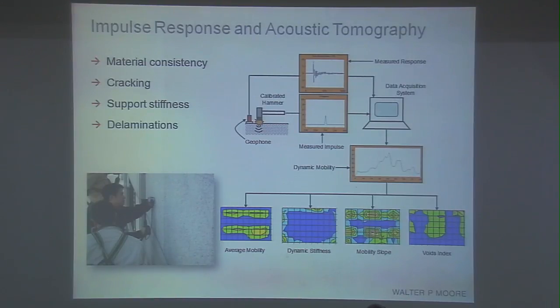By doing that, you can estimate cracking, you can determine anomalies within the structure. And so if there's particular areas where the wave speed is much slower, it can be indicative of voids or cracking, things like that. And so this tool can allow you to look through quite a large thickness of concrete with the acoustic tomography, although you do generally need access to more than one side of the structure in order to accomplish that. So that can be an impediment to it, but impulse response can usually be done on one surface, but will give you more of a surface profile.